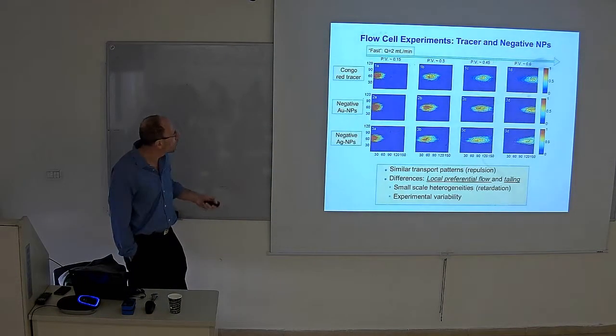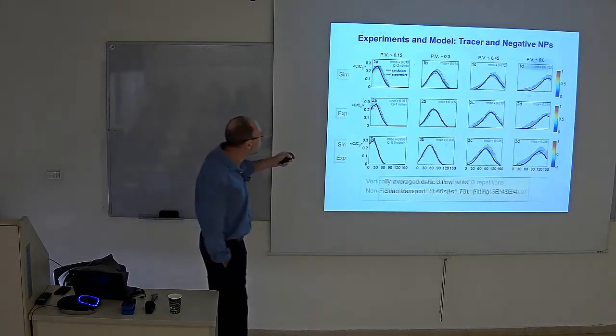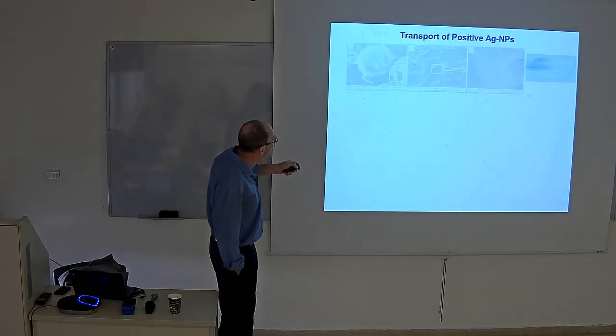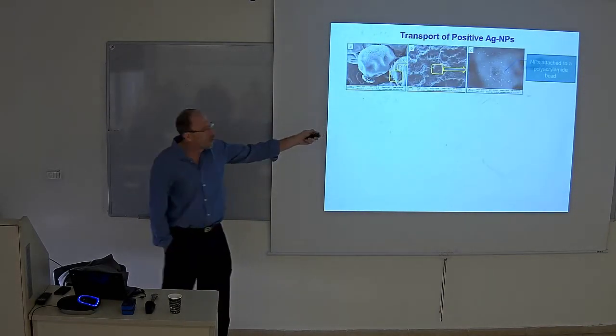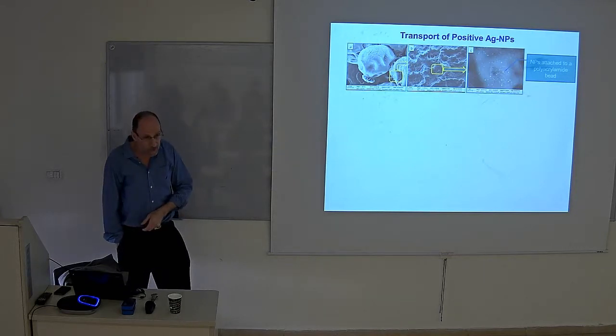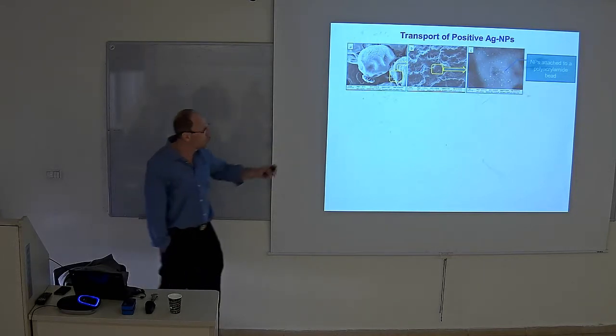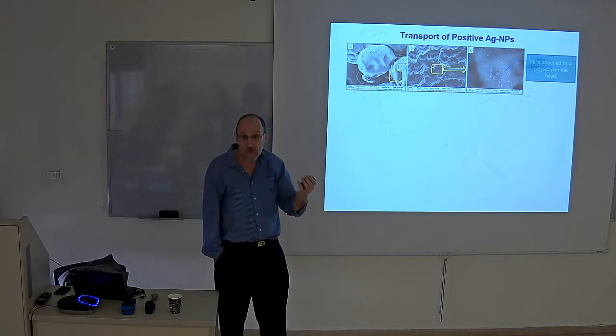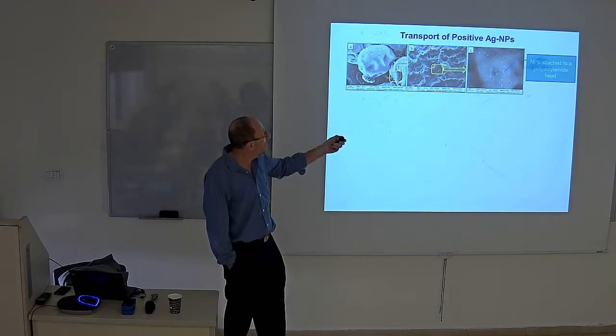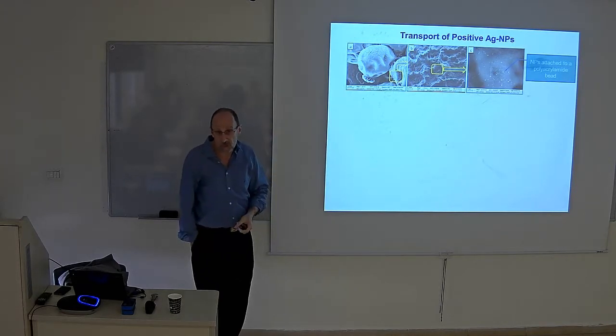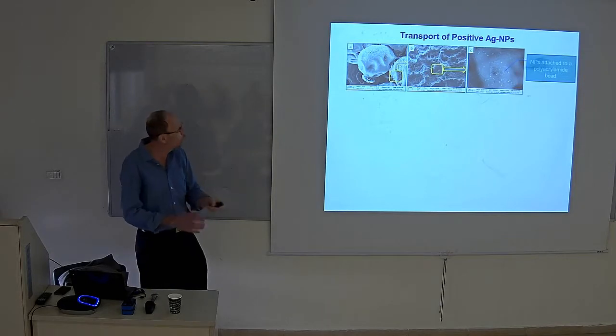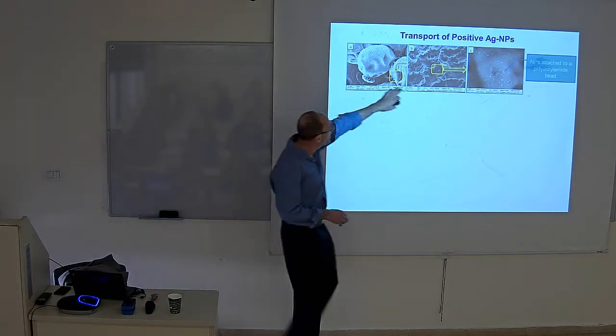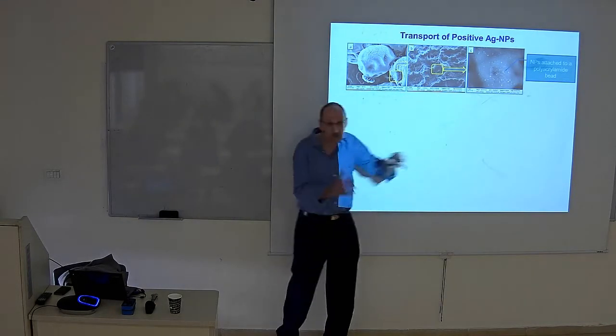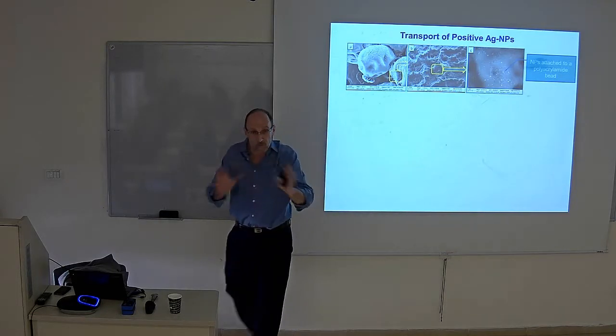We did a whole series of experiments that I won't go into in the time. But what I wanted to mention here was we looked at positively charged silver nanoparticles. Okay? Now, the beads that we were working with, the porous medium, is negatively charged. These had a citrate coating, they're positively charged. So we said, great, this should be a very simple experiment. You can see the beads here, exposed to the nanoparticles, they're attached, positive, negative, they don't move, that's it.